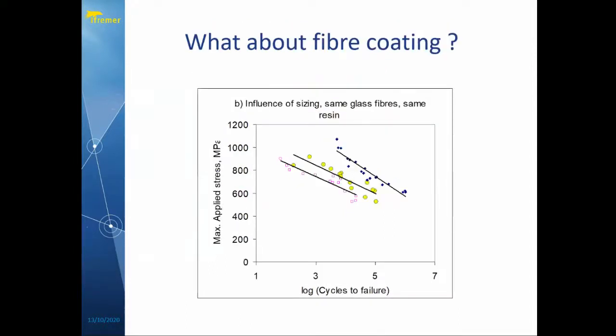There are other parameters. One of them is fiber coating. So fiber sizing on glass fibers is very important. And this is just a set of three sets of fatigue tests on very similar materials. The only difference is the coating. And you can see we can shift the SN curve from the optimized material here on the right. It can shift it maybe a decade or more left if you don't use an optimized fiber coating. But this is the glass fiber manufacturer's know-how, and it's an extreme case to show that it does affect fatigue performance, but in general you can optimize this when you get your reinforcement selected.